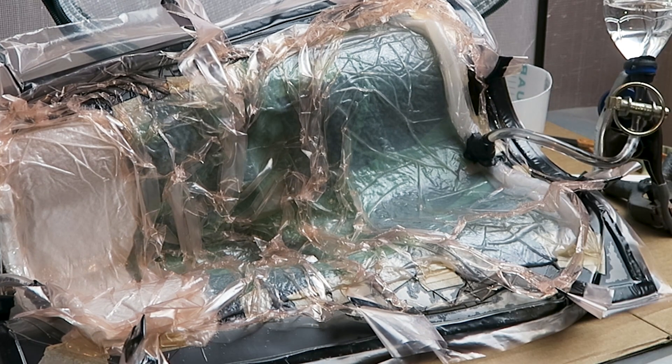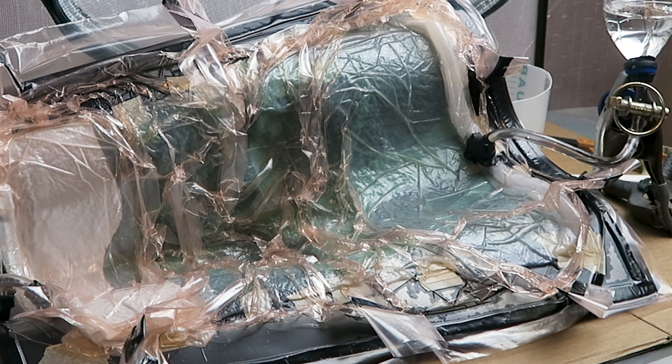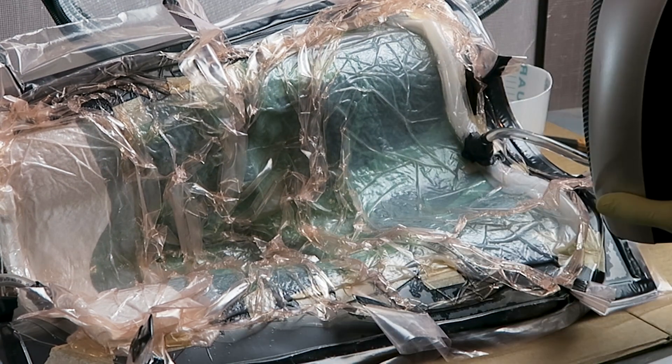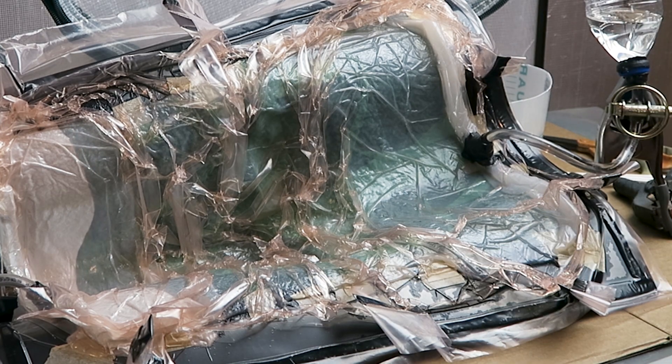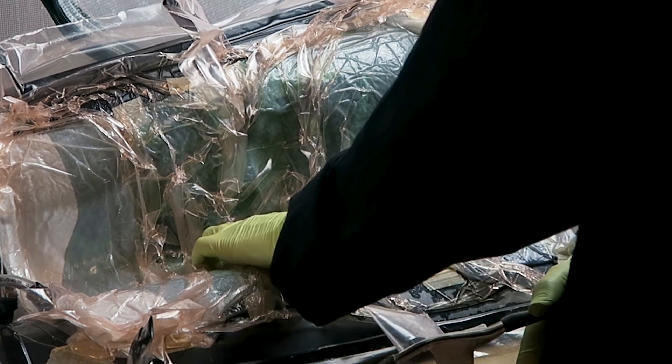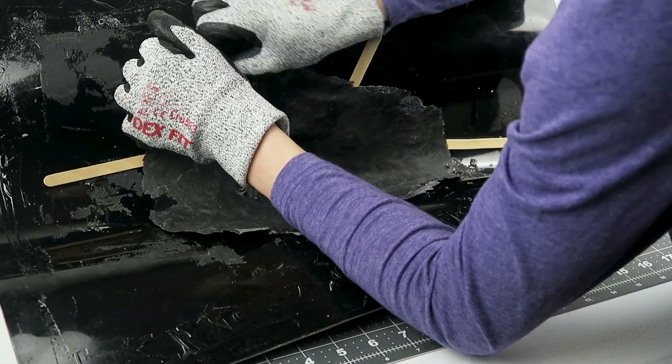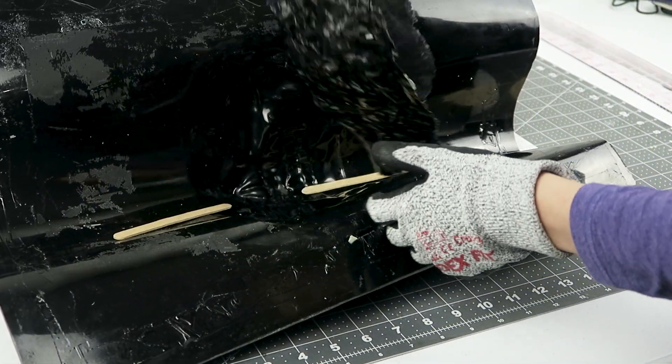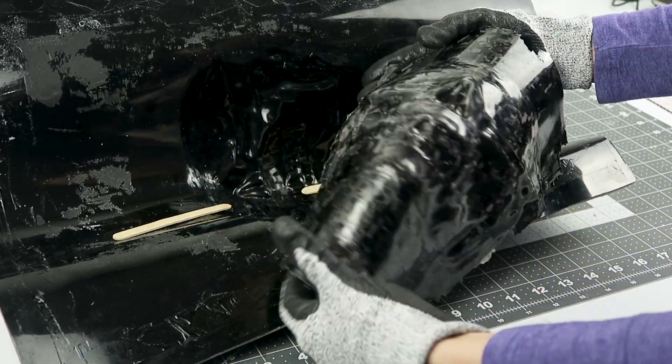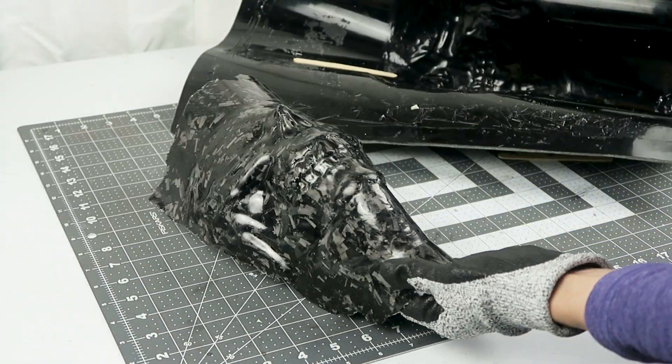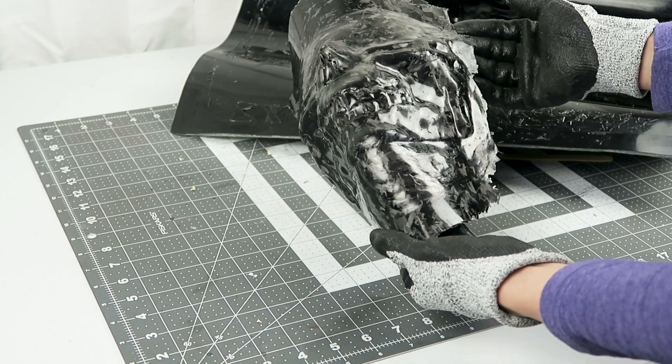So to save the part and get at least some compression, I placed the entire mold after infusion into a separate vacuum bag and vacuumed out all the air to compress it as much as possible. That did help and it allowed the part to be at least close to usable, but with all that air that got in there and the loss of compression, the fabric wasn't properly pressed against the mold and that's where the issue came.